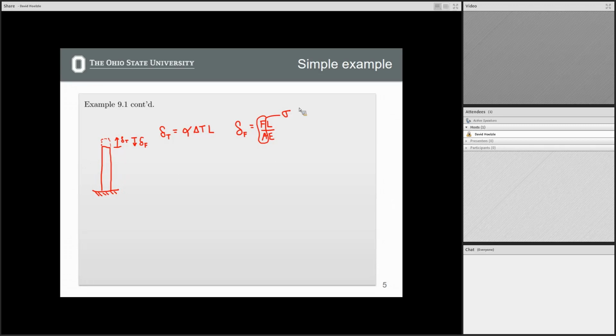Okay. So if we want this system to be basically in equilibrium here, we have to have delta T minus delta F equal to 0. And so putting these equal to each other, we get alpha delta T L minus sigma L over E is equal to 0. L's cancel out. And so then I get sigma equal to alpha delta T times the Young's modulus for this material. Okay. Any questions on this simple example?